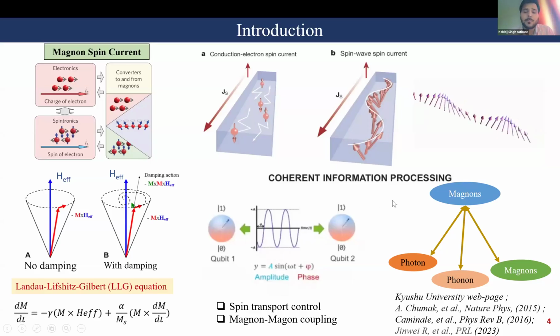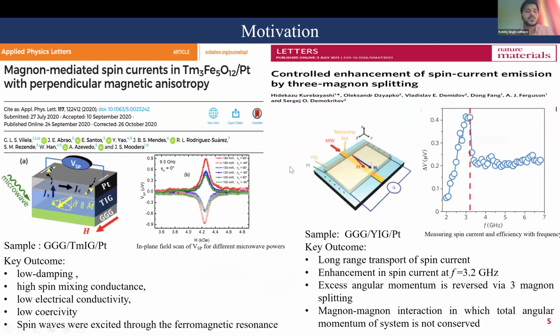In these hybrid magnonic devices, we can also tune this coherent information processing via the coupling between magnons and phonons, magnons and photons, or magnons and magnons. Basically, this all boils down to two basic points: the control of the spin wave current and the coupling between the magnons. For this, the chosen media were ferrimagnetic insulators like TMIG and YIG because of their ultra-low damping, high spin mixing conductance, low electrical conductivity, and low coercivity too.